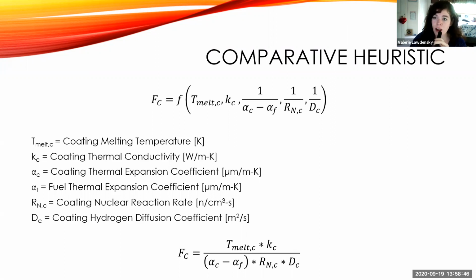The thermal conductivity, obviously, we need that heat transfer. That is one of the actual limitations of this particular reactor, isn't how much heat is produced, but how much heat we can remove effectively. And then the thermal expansion coefficient compared to the fuel's thermal expansion coefficient. So that difference is very important to us. That coating's nuclear reaction rate, basically we don't want a coating to reduce it. There are some coatings that will act as poison and actually reduce a nuclear reaction, which kind of defeats the purpose of their use in a nuclear reactor.